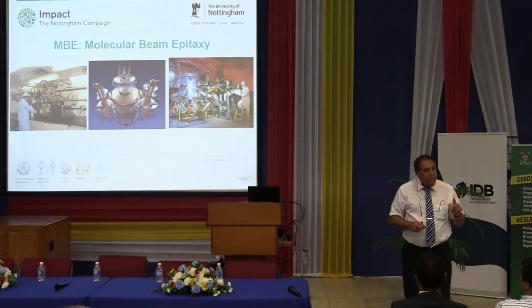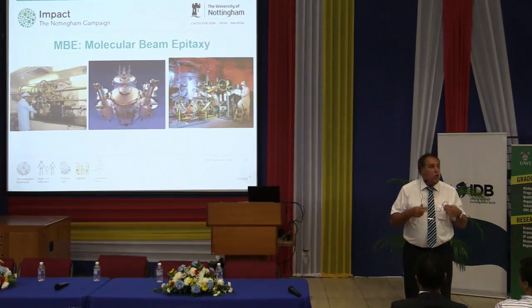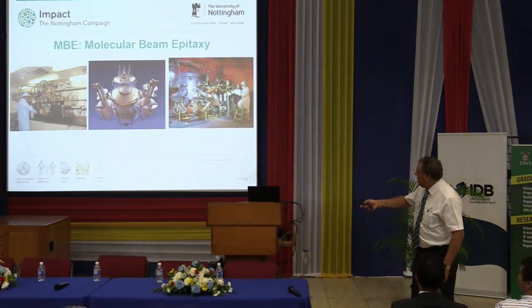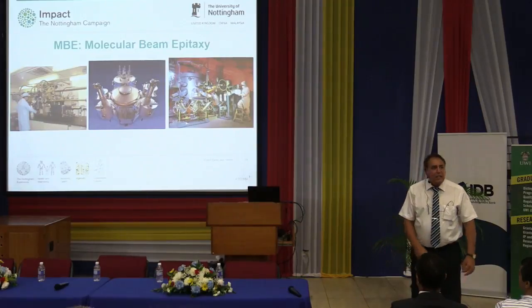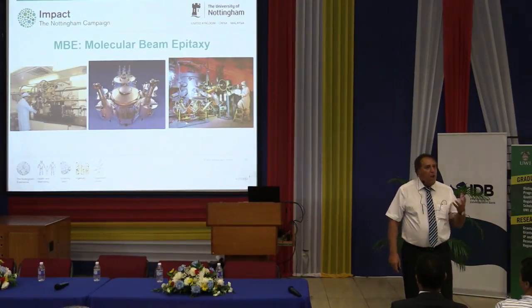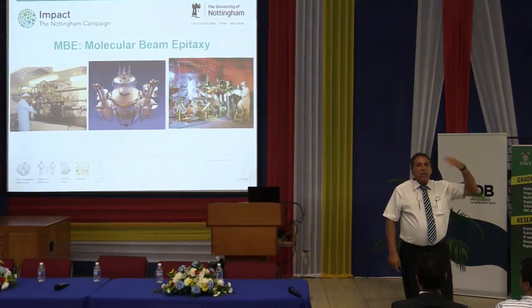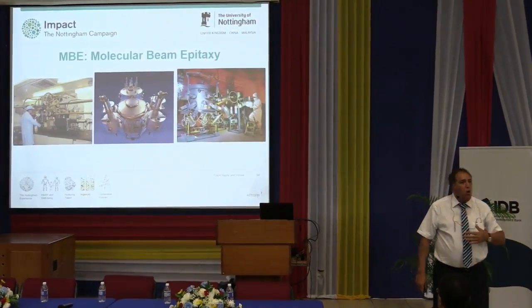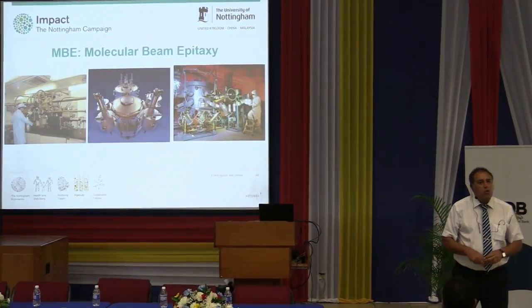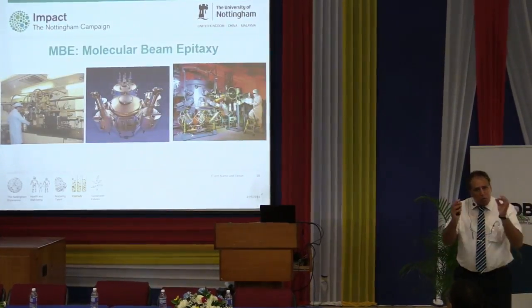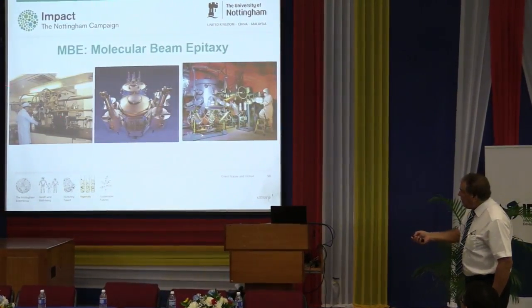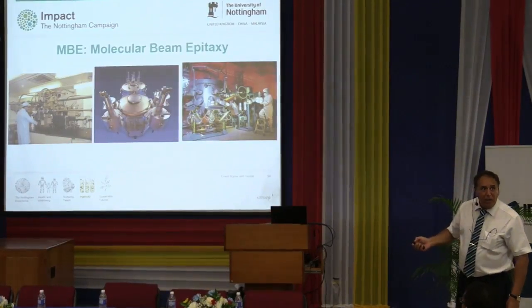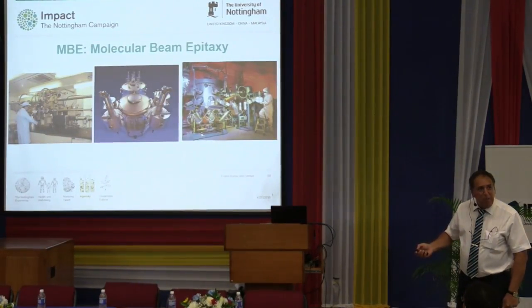But this kind of deposition is made in very ultra-high vacuum conditions. That means the number of foreign atoms in this space here, where we do the growth, is practically zero. You only have the atoms which you are evaporating. It's like in outer space, where you have fewer and fewer molecules. That's exactly what we do on Earth. We pump out all those foreign molecules, and we have only the ones which we want to evaporate. So this was very expensive, £1.5 million in 85. That was big money in those days.